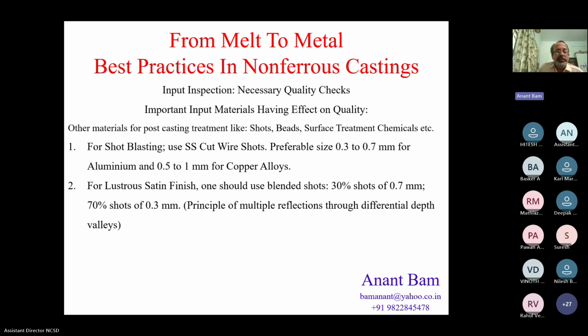For aluminum shot blasting, stainless steel cut wire shots are highly preferred. I recommend them because they last long and they do not break easily. They do not deliver their own color onto the casting. Preferable size is 0.3 mm to 0.7 mm for aluminum and 0.5 mm to 1 mm for copper alloys.